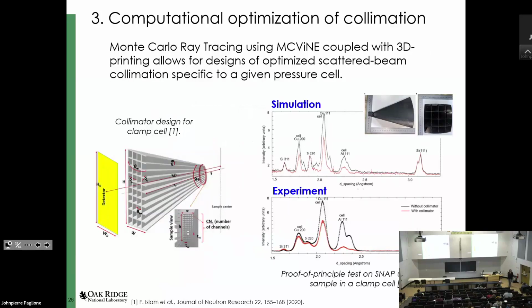We have been taking that to a next step to optimize these scattered beam collimators through McVine. So this is Monte Carlo ray tracing, where you can actually simulate the instrument, the sample environment, so the pressure cell you put in the beam, and the scattered geometry to really optimize what arrives at the detector. I don't want to talk through that in detail. I just want to show you this is a very complex optimization. So this is why it needs to be computer driven. You would not be doing that manually. And so we printed just a few test pieces where, again, here you see the example of the cell, so the scatter you don't want without the collimator, and how much is reduced when the collimator is added. So these things are complex and they're still work in progress, but they do add a lot.